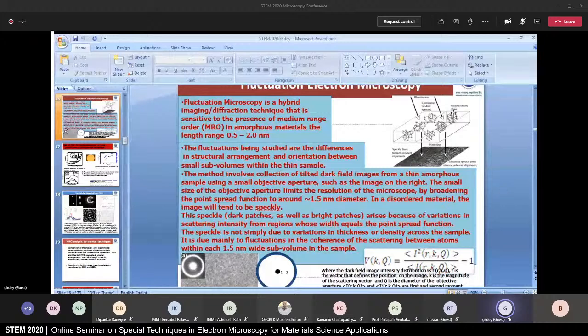So if you get an image, you will have speckles in the image, and this is actually the diffraction pattern. What you are targeting is the intensity diffracted in this region, which we never used to focus earlier. But in this case, we are actually talking about the intensity in this region. You can either use it in the image mode, or you can use it in the diffraction mode. In either case, this intensity is a representation of the medium range order in a disordered solid like this.